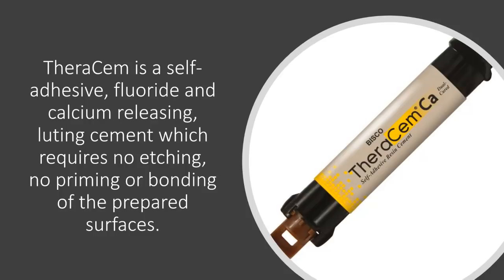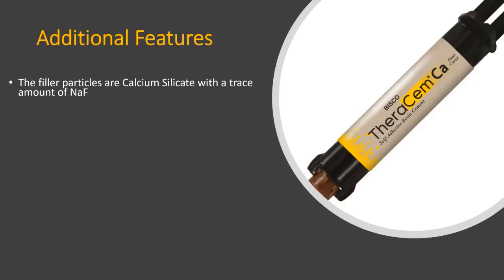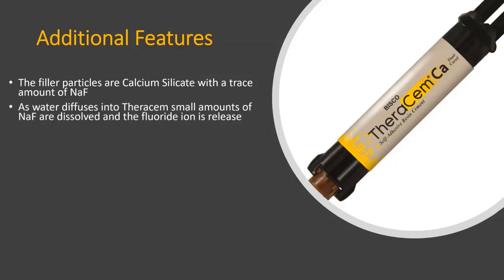You don't etch the tooth, you don't prime, you don't even have to prime the surfaces for zirconia because of its chemistry. So here's what most people don't know. The filler particles within the resin are calcium silicate, with a trace of sodium fluoride. So as water and saliva diffuse into the Theracem cement, small amounts of sodium fluoride are dissolved. And this is when the fluoride ion is released, and it's a small amount.